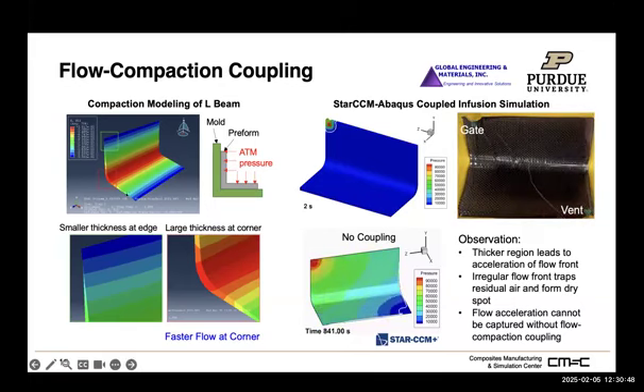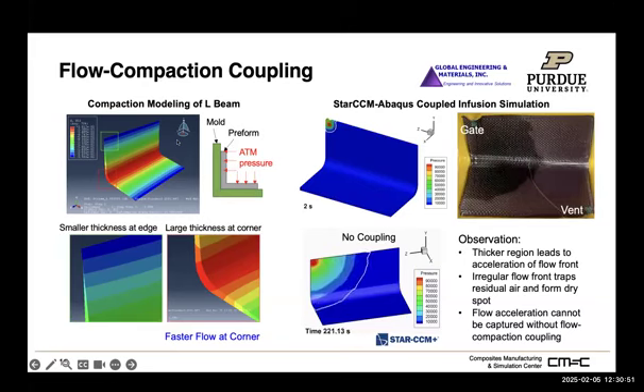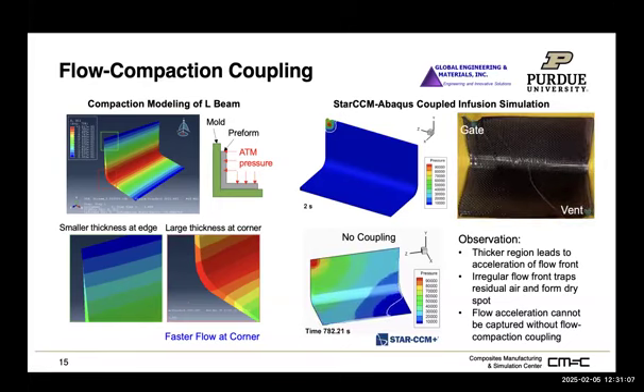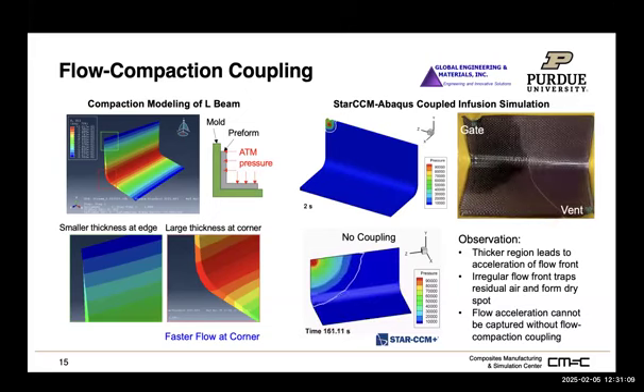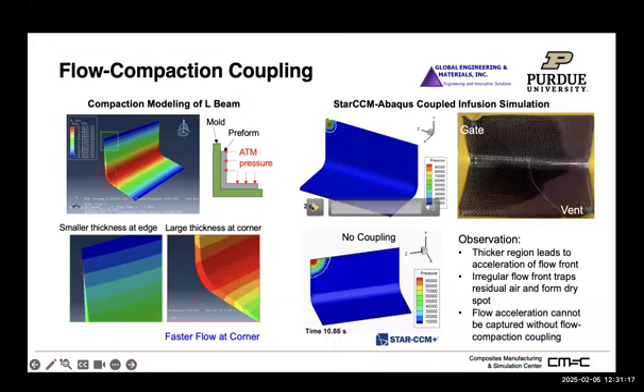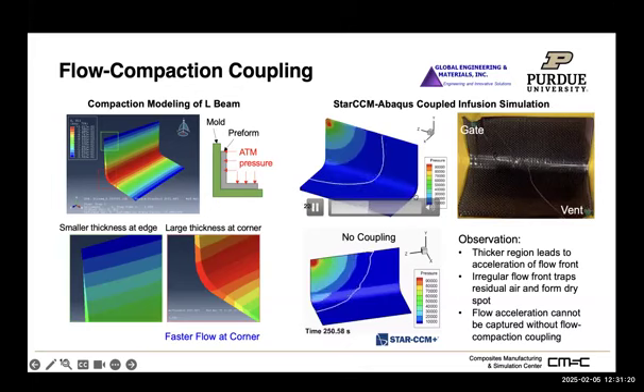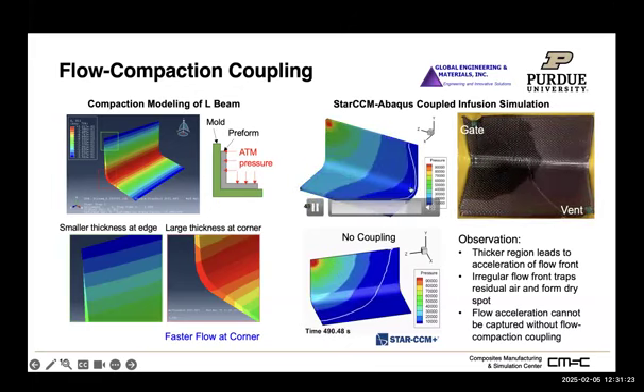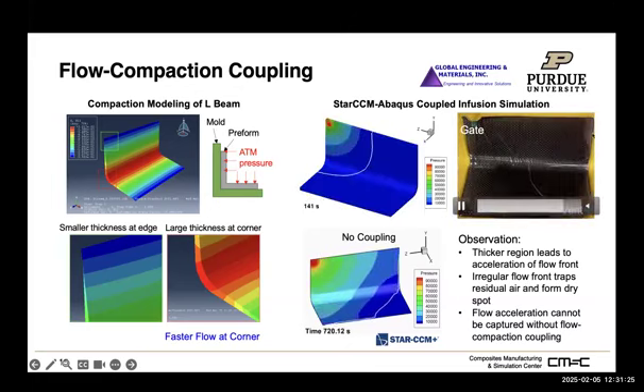So that triggered us to look back at our fabric model to understand what compaction happens at the corner. From the fabric simulation, we definitely expect the thickness at the corner to be slightly thicker than at the edge of the panel. So we have to account for the fact that the compaction force will affect the permeability, and incorporate that effect into the simulation so that we capture something very similar to what we see in our experiment.